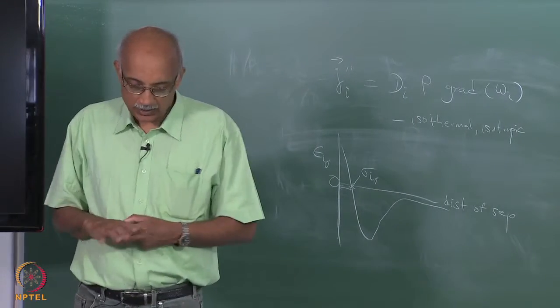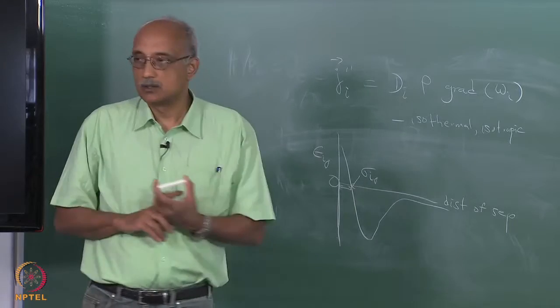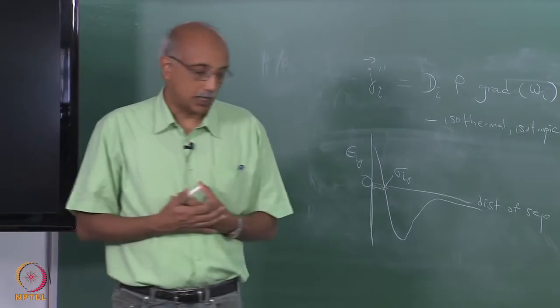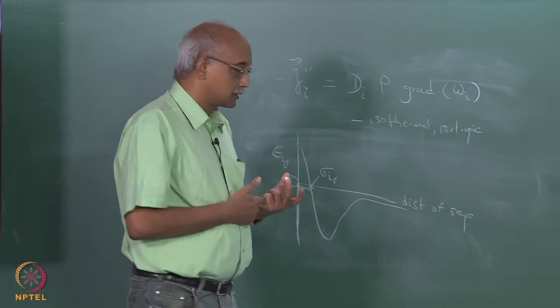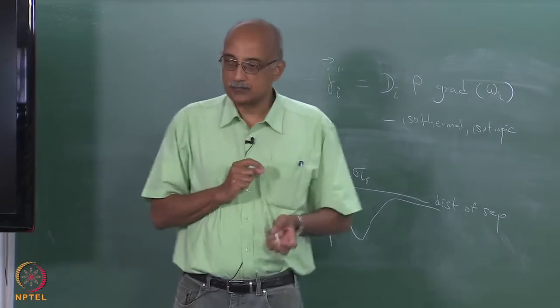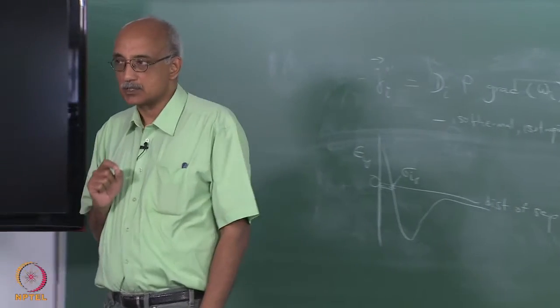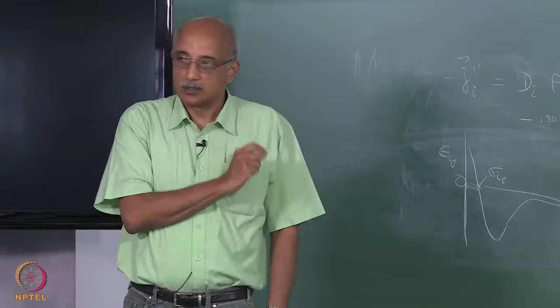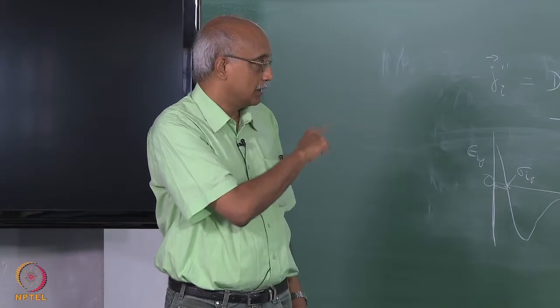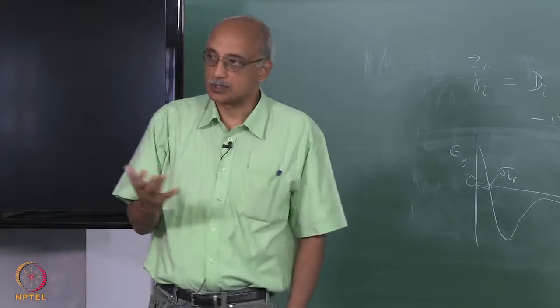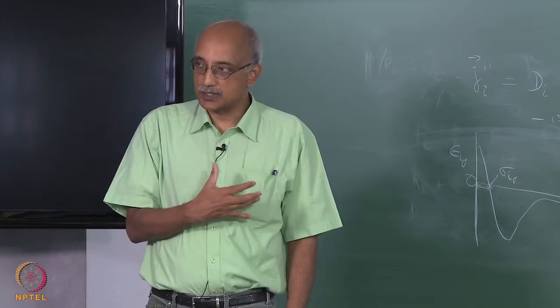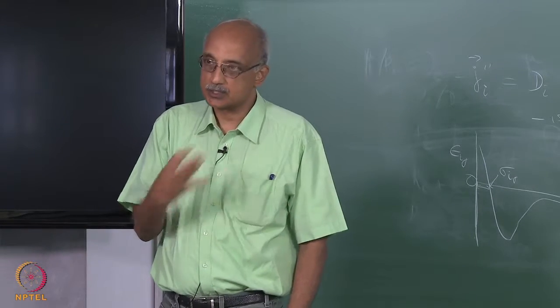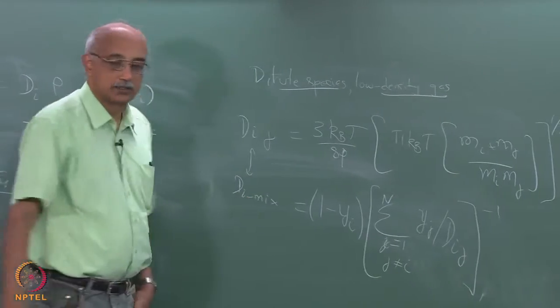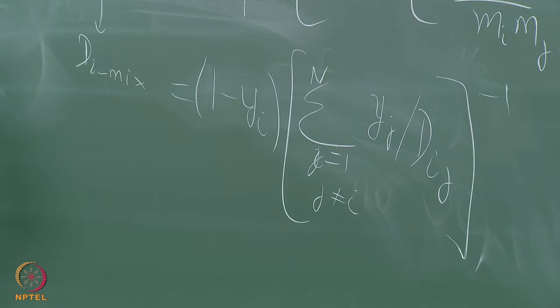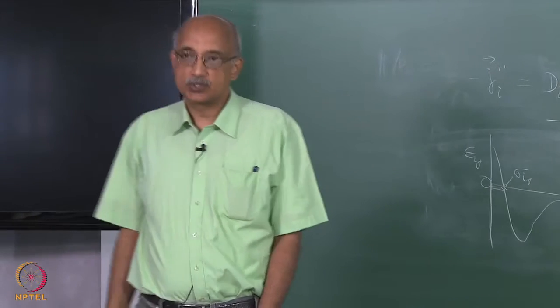So, once you have estimated the diffusivity of species i in the mixture, again we are assuming that it is a single parameter for the system, which means we are still assuming isotropic. The only assumption we have relaxed here is the binary assumption. We are allowing multiple species to be present and we have estimated the diffusion coefficient in the presence of multiple species, but the fact that we only have a single scalar value for Di mix essentially implies that we are still assuming it is an isotropic fluid and that the diffusivity in every direction is the same.